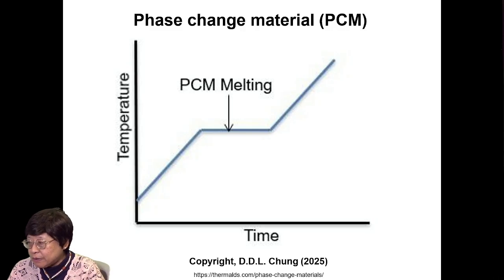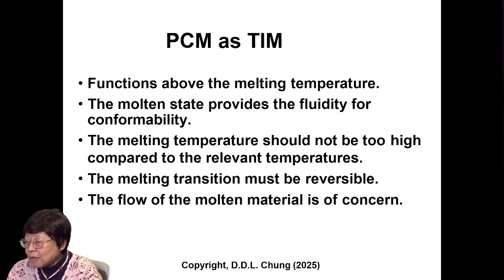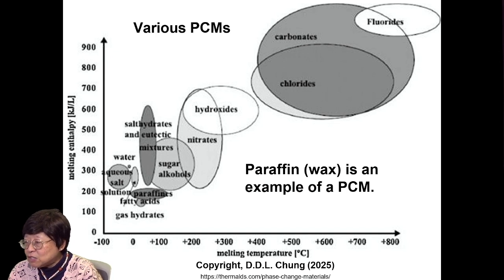Next, consider phase change material, or PCM, and the phase change is melting. Through melting, the TIM becomes conformable, or at least more conformable, and so the TIM performance becomes better. The PCM, or phase change material, functions above the melting temperature, and the molten state provides the fluidity for conformability. The melting temperature should not be too high compared to the relevant temperatures. The melting transition must be reversible. The flow of the molten material is of some concern. There are many types of phase change materials, but we want those at the low temperature range typically. So paraffin or wax is an example.